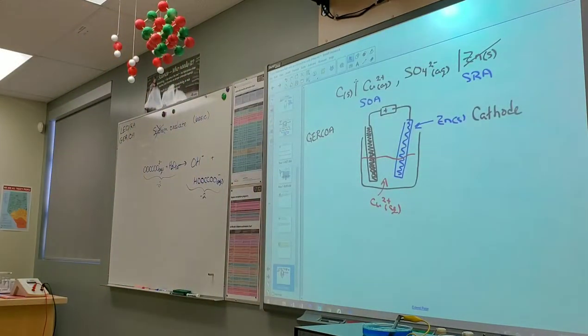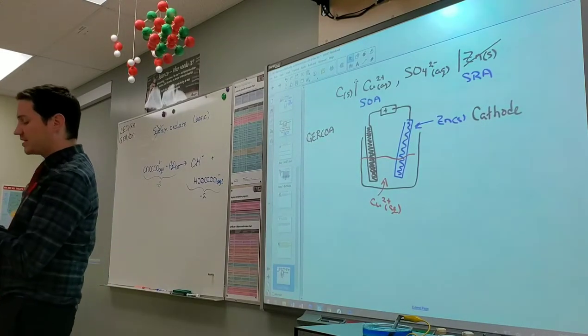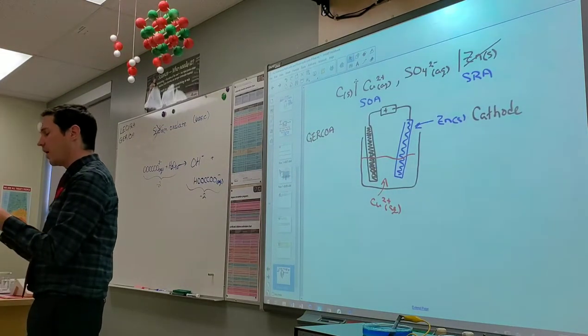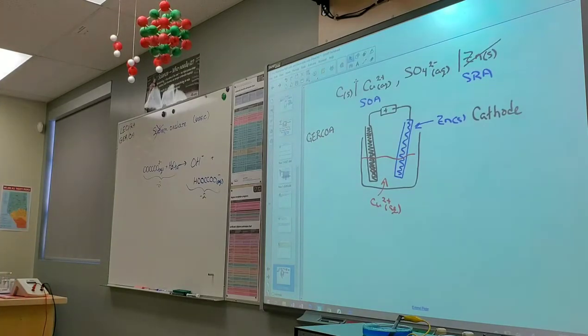We've got lots of scrap chunks of metal out in the lab, okay? So for example, I took a penny, and a penny is covered absolutely with the metal that would react spontaneously with copper, and I forced it overnight on a really tiny low voltage. I forced it overnight to react, and I coated it with a small amount of copper metal.